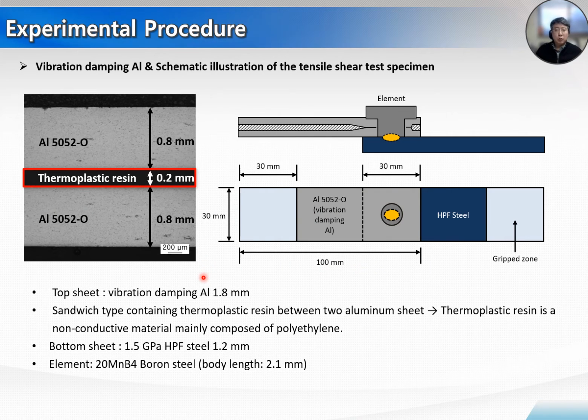For the experimental approaches, the vibration damping aluminum and a schematic illustration of the tensile shear test specimen are shown here. The top sheet, vibration damping aluminum, is a total of 1.8 millimeter thickness, and the thermoplastic resin has about 0.2 millimeter thickness. The sandwich type contains thermoplastic resin between two aluminum sheets, a non-conductive material mainly composed of polyethylene. The bottom sheet is the 1.5 gigapascal hot press formed steel with a thickness of 1.2 millimeter, and the element is the 20MnB4 boron steel, and the body length is 2.1 millimeter.